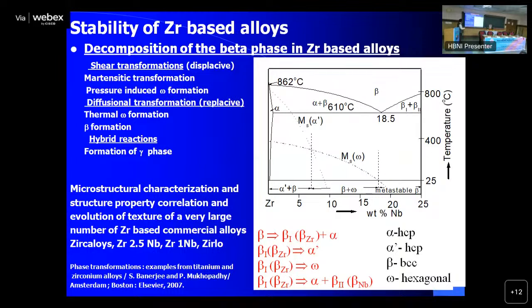So just to have a quick recap, here we have the stable phases, alpha zirconium, beta zirconium. These are the metastable phases, alpha prime, which is the martensite, and omega, which is also a metastable phase, hexagonal phase. These are some of the phase reactions. This is the equilibrium phase reaction, and this is involving metastable phase. Okay, so here is the region where martensites will form,